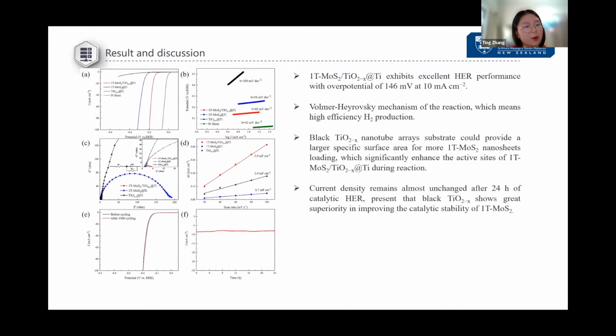To further analyze the HER property, we did the LSV test and compared it under the current density of 10 milliamp. We got the conclusion that the high content 1T-MoS2 with the help of the black titanium dioxide nanotube array substrate exhibits the smallest overpotential. It's around 146 millivolt. And because of the high content of the 1T-MoS2, it also exhibits the smallest electron transfer resistance in the catalyst. And due to the help of the black titanium dioxide nanotube substrate, the active sites exposed to the electrolyte during the reaction are the highest.